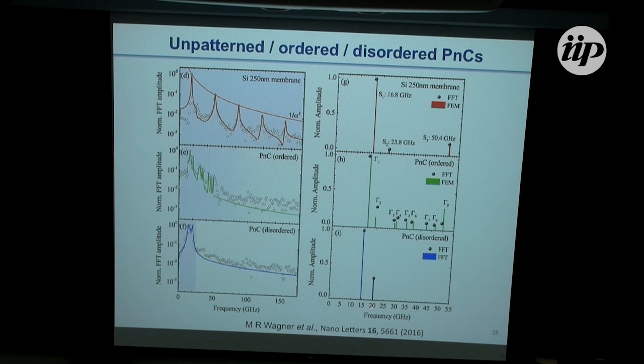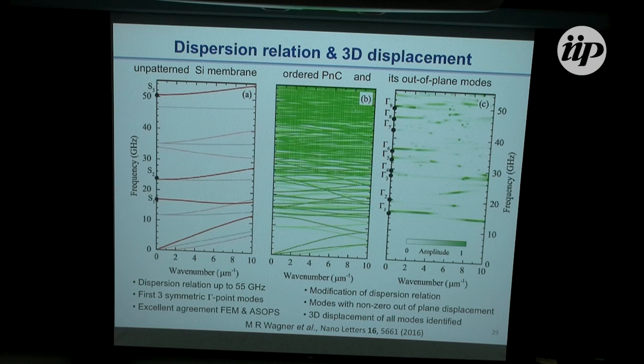Or rather, on the mode distribution of the lifetime of the phonons. And here you have a little bit more explicitly the frequencies that are involved. These are ascribed to the frequencies observed in Brillouin light scattering. The membrane dispersion relation, as we know it, is here, and in the time domain we can identify very well the gamma equals 0 frequencies.